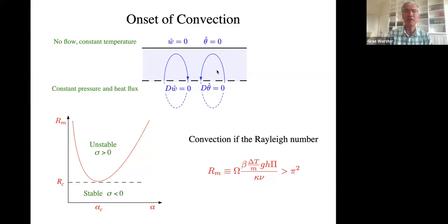That we will get convection inside sea ice if the Rayleigh number exceeds a value of about 10. And we see that this Rayleigh number is proportional to the thickness, h, the thickness of the sea ice, and some other parameters. Okay, the permeability, the temperature difference, the viscosity nu, the diffusivity kappa, and so on. But I want to focus on the fact that the Rayleigh number is proportional to the thickness. And let's look at that experimentally.